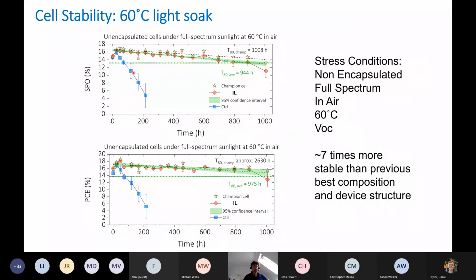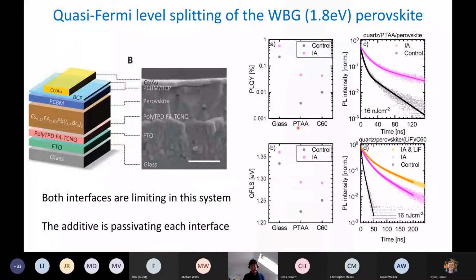These are cells measured. SPO stands for steady state power output. So cells measured under 60 degrees, non-encapsulated under light, sunlight, and the sort of lifetimes is getting up to many thousands of hours for the best cells. What we want to understand is, why does it improve the stability, and why does it also improve the open circuit voltage? And I'll just show a couple of slides here where what I'm showing is the photoluminescence quantum yield